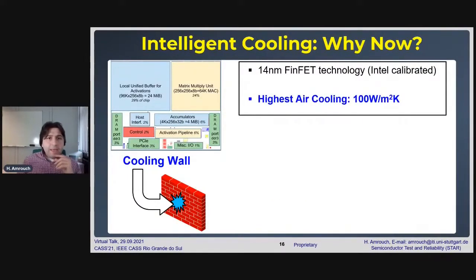But we have a problem. In such complex systems, if we take a look at the picture here, which is from ISCA 2017 from Google, the first version of the TPU, we can observe that a large portion of the chip is dedicated to the systolic MAC array. The systolic MAC array consists, in this example, of 64,000 MAC units. And these 64,000 MAC units are all confined in a very tiny area, which is 24% of the chip. This is really a problem because it will consume huge power confined in a very small area and will lead very quickly to excessive heat generation.